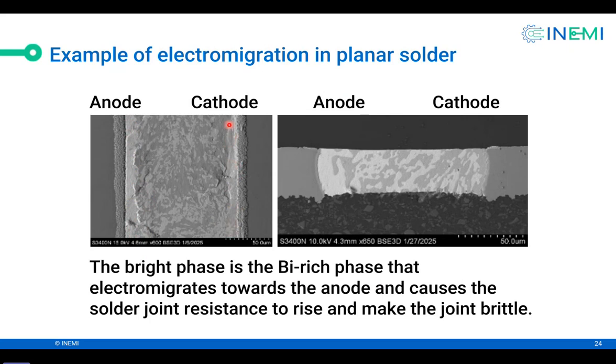It's become more grayish, but it's more clear in the cross section. So this is the bismuth segregation on the anode. And here, the gray region is the tin-rich region which got left behind because bismuth moved to the left. So the bright region is the bismuth-rich phase, which electromigrates to the anode, and it causes the resistance to increase